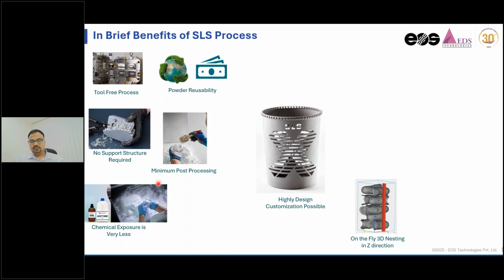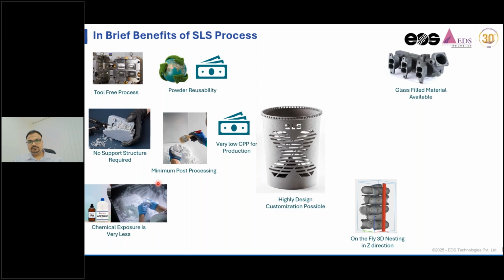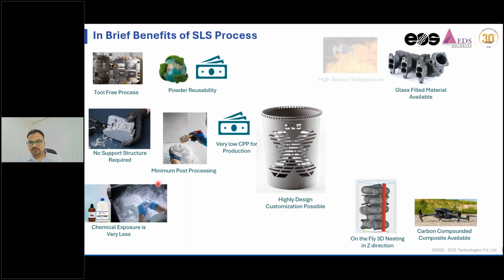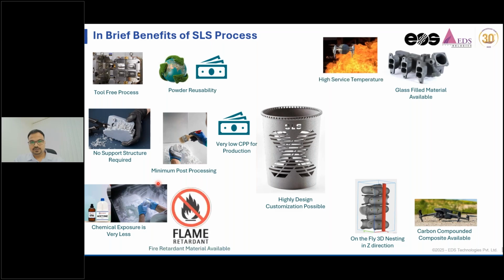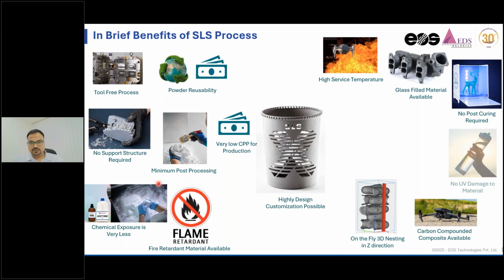You can directly fill the components as many as possible in this space and use the printer as a production machine. And this makes the cost of printing the component very low. We have, as I said, glass filled materials which are more robustly used in high strength polymers. We have high temperature service material and flame retardant material with us. There's no post curing, as I mentioned, not much post processing, so there is no curing, and just immediately after printing the parts are usable.